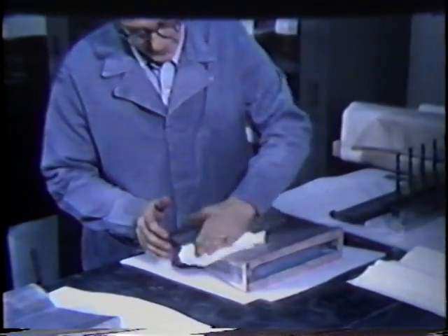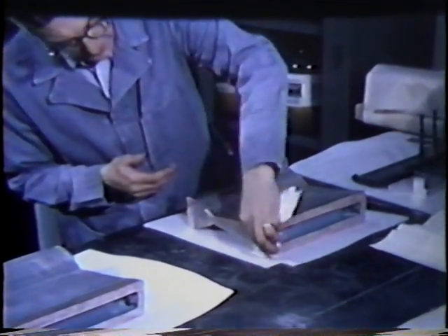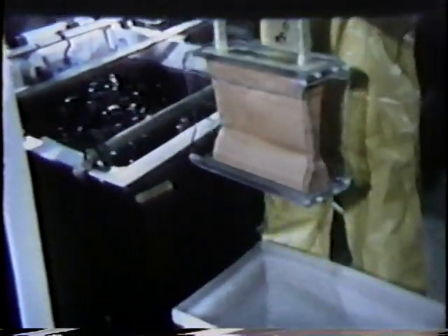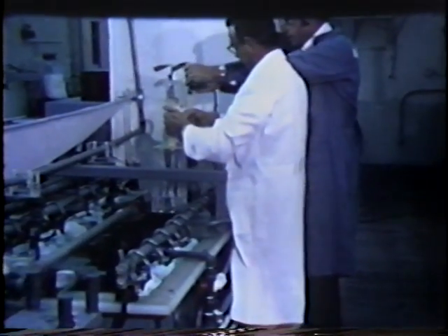Preparation of the assembly for electroforming is completed by coating the Rigidex with a silver powder to make it conductive, enabling deposition of copper to take place. The use of a copper barrier between the region of hydrogen flow and the electroformed nickel was found in earlier studies to be one means of avoiding hydrogen embrittlement of nickel. The nickel plating which follows is completed in three steps.